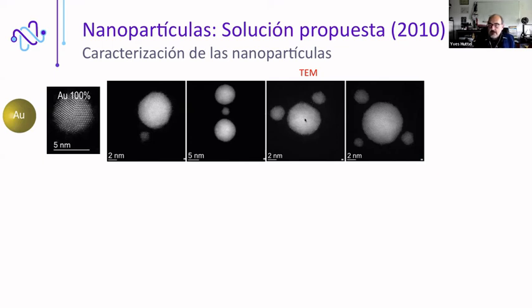This is not a random process. When we inject water, we have this kind of structures. And when we do not inject water, we have a single nanoparticle with one specific size. But when we inject water, we have a teeny layer of water that makes the small and big nanoparticles stick together and form these Mickey Mouse structures.